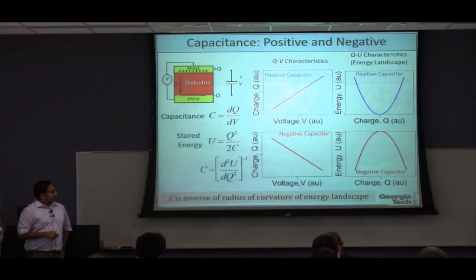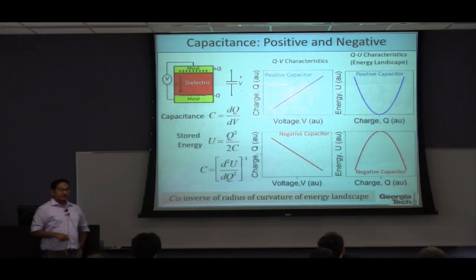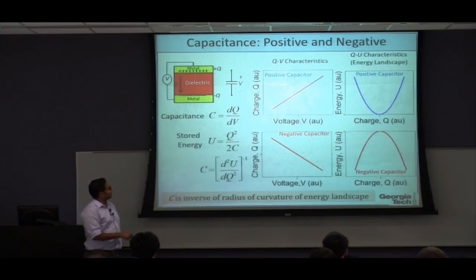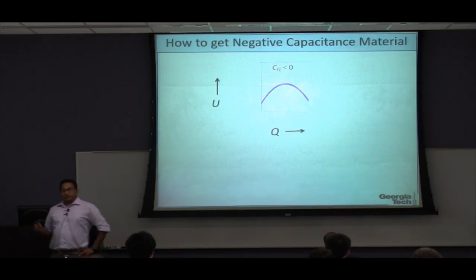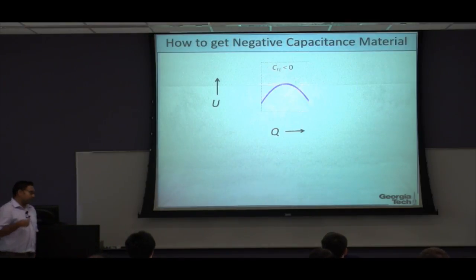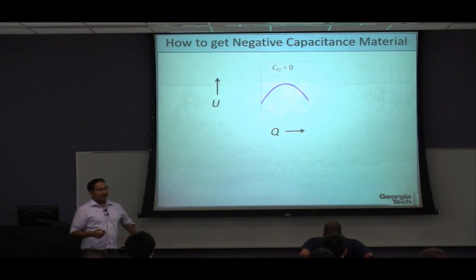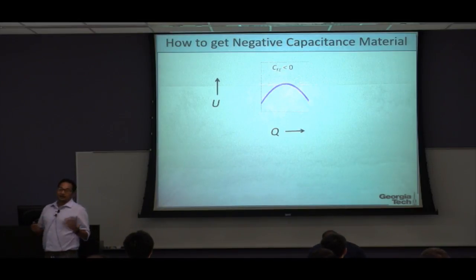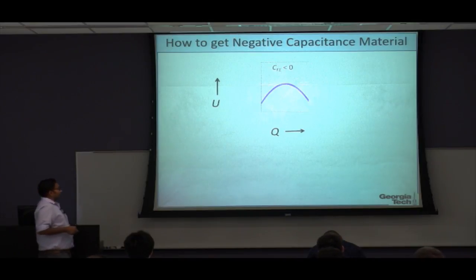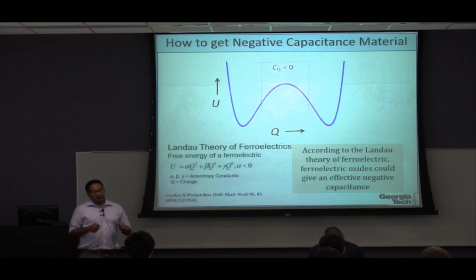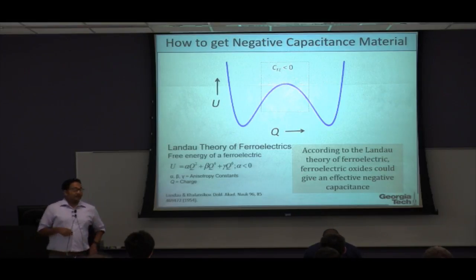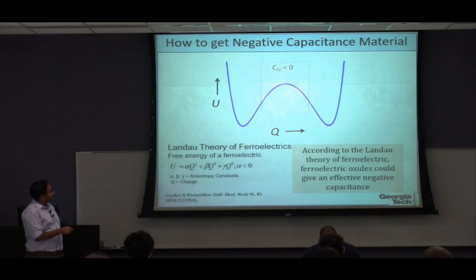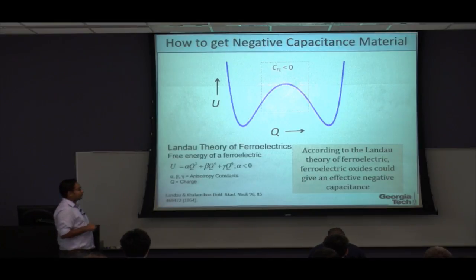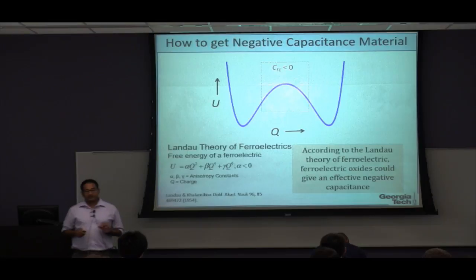On the other hand, if you take a negative capacitor material, the energy-charge characteristics will look like an inverted parabola, and the radius of curvature will actually be negative. So the first question that we started with was, do we know of any material that has an energy landscape that looks like an inverted parabola? And the answer is that, according to the Landau theory of ferroelectrics, a ferroelectric material can have an energy landscape like this, a double well potential, where the capacitance is negative in a certain range of charge. So that's the basic idea: a ferroelectric material, in theory, can give a negative capacitance.